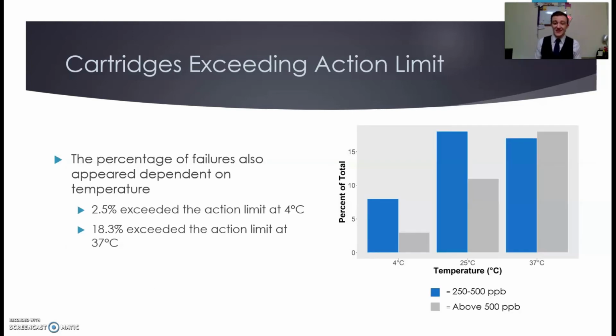This plot summarizes the data in a similar fashion, but instead of comparing manufacturers, we're comparing temperatures. And it really starts to illustrate that the higher temperature environments generally saw an increase in metal leaching compared to the lower temperature environments, with the 37 degrees Celsius environment showing higher concentrations in that gray 500 parts per billion range and in the 250 to 500 parts per billion range than the 25 degrees Celsius and the 4 degrees Celsius environment respectively. Therefore, it does show that there is some dependence on temperature as well in determining how much nickel is leached into these products.